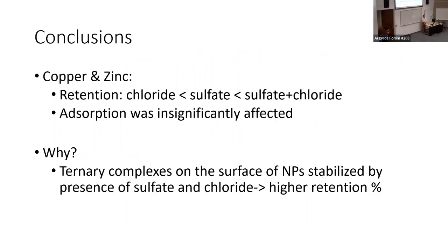So what are our conclusions? We saw very similar data for both copper and zinc. So we concluded that the retention increased from the presence of just chloride, just sulfate, and the combination of sulfate and chloride was the greatest. We saw the adsorption, which was the top curves on those graphs, was not greatly affected by adding sulfate or chloride or the combination. But we did see when we added those amounts, we did get that uptake.